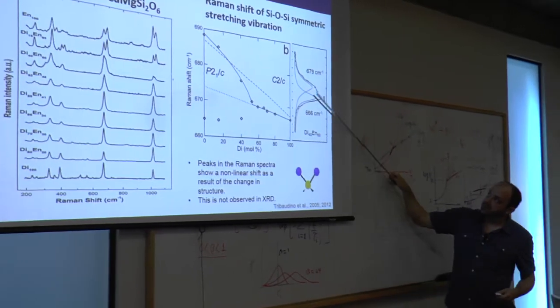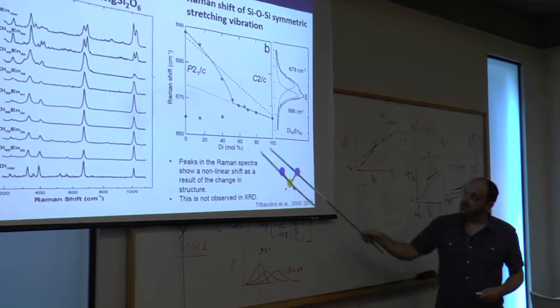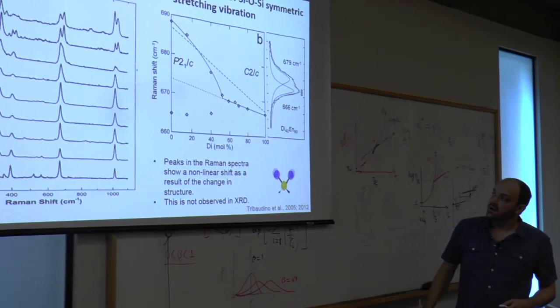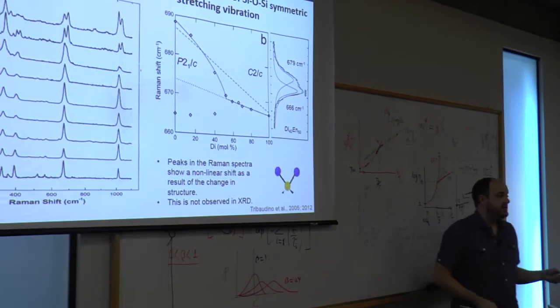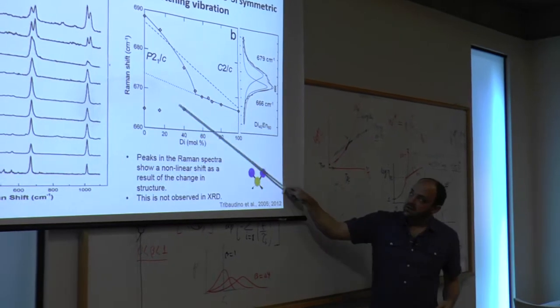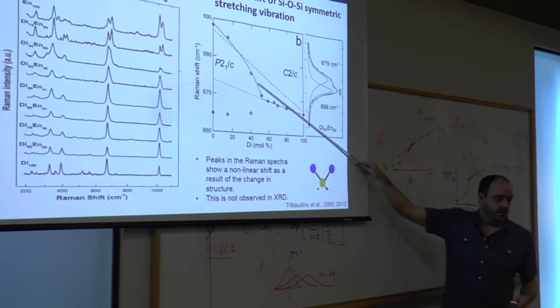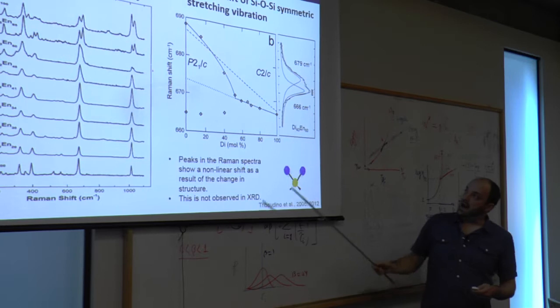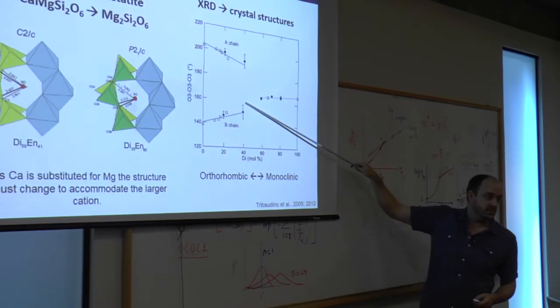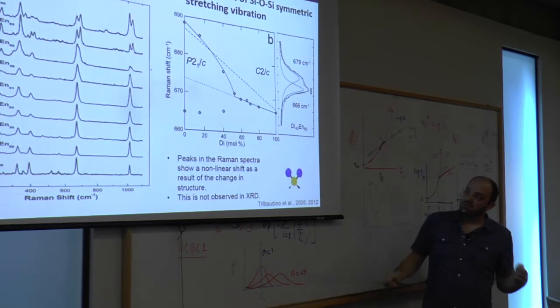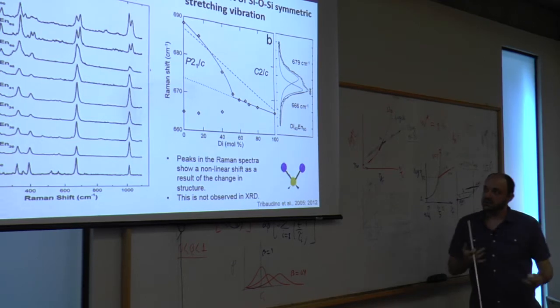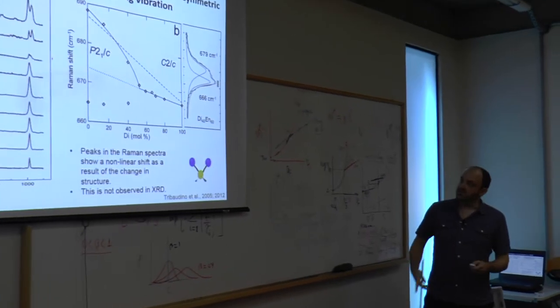And they did a model of two curves for the two chains and one for the other one. It shows the sensitivity of Raman: we're actually seeing these bonds flex and change, and not just collapse in a dramatic sharp change here. So the Raman is much more sensitive to these small changes in the bonds and how much force you place on them.